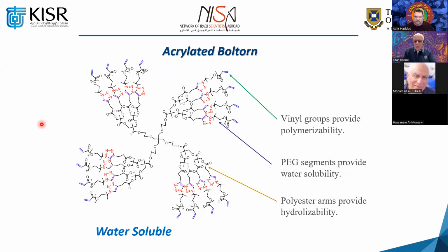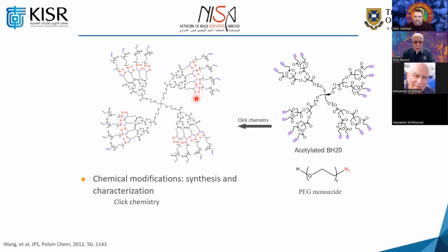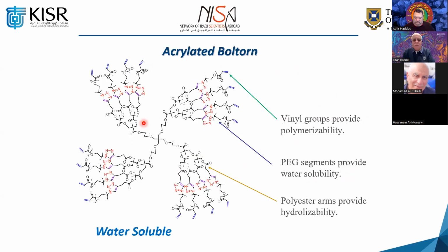So we end up, here you could see the acrylate group, and this is a click, and then we polymerize it, okay? So we created that molecule, that nanoparticle. As I mentioned earlier, the original nanoparticle is not water soluble, it's hydrophobic. By introducing polyethylene glycol, we made it more soluble in water. And also it depends on how long this polymer chain is.